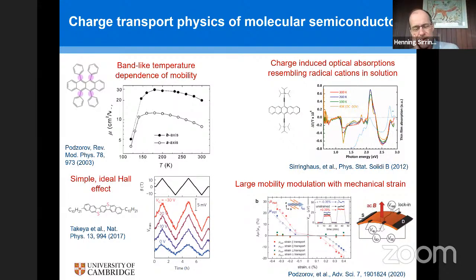And what's quite strange is that these optical absorptions look very similar in many cases to what you would see if you were dissolving these molecules in a solvent, so completely isolating them, and then charging them chemically. You can extract an electron by some chemical doping process, and then look at that charged molecule in solution. And these absorption spectra that you measure in the solid state look very similar to the ones in solution, which tells you that probably we are not talking about completely delocalized Bloch electrons here, but about electronic states that are more localized, maybe not to individual molecules, but to a small number of molecules.